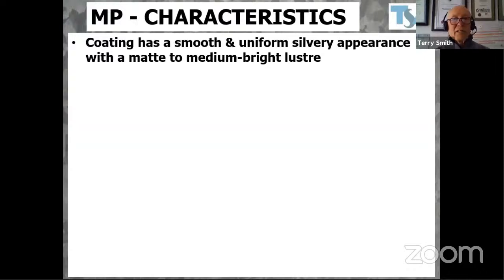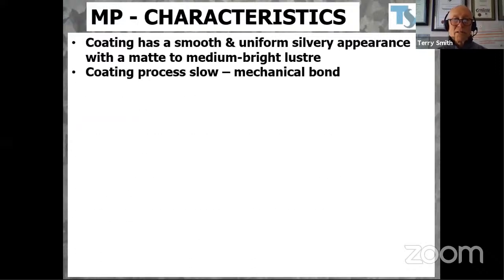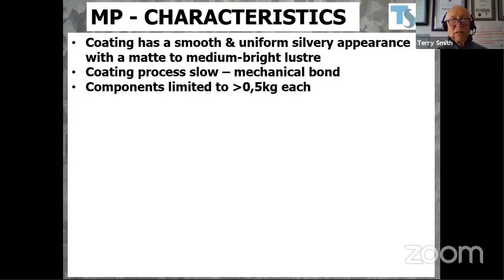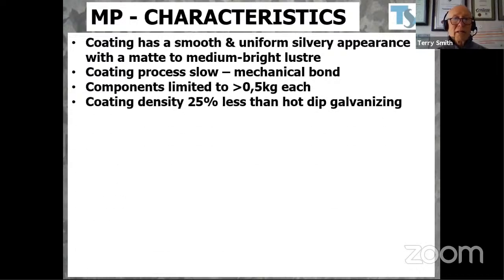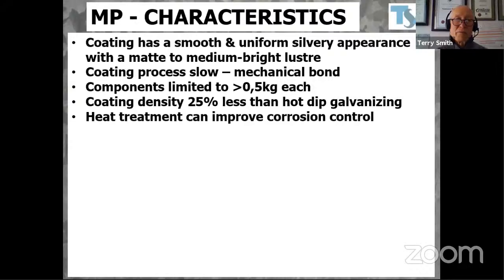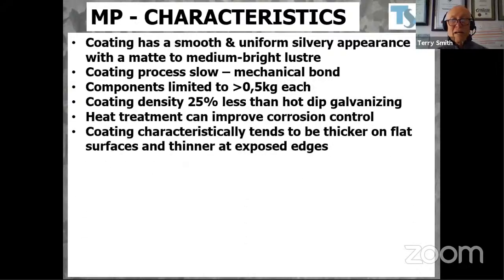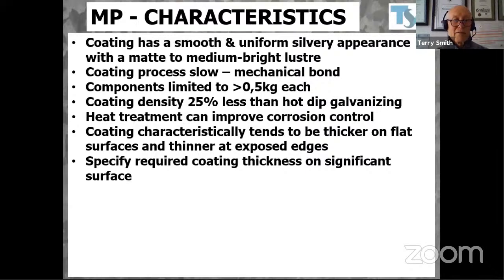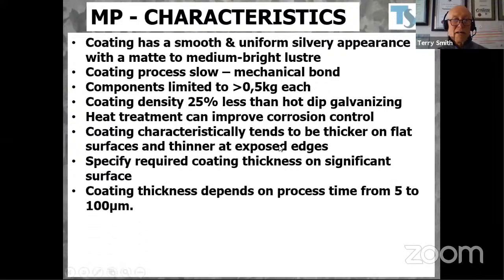The characteristics: coating is smooth, uniform silvery appearance with a matte to medium bright luster. Coating process is rather slow, and it's a mechanical bond. Components are limited to less than or just on 0.5 of a kilogram each. Coating density is 25% less than hot dip galvanizing. Heat treatment can improve the corrosion control. Coating characteristically tends to be thicker on the flat surfaces and thinner on the exposed edges, and therefore it's important to specify the right coating thickness on the specified significant surface. Coating thickness depends on process time, from about 5 to 100 microns.